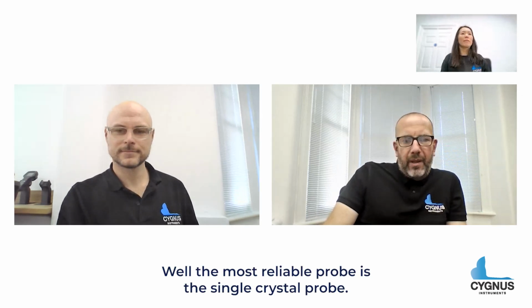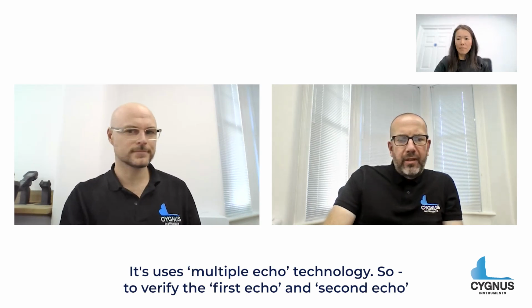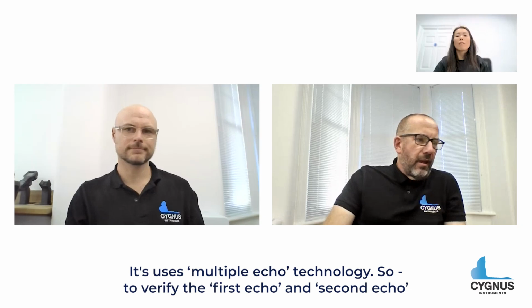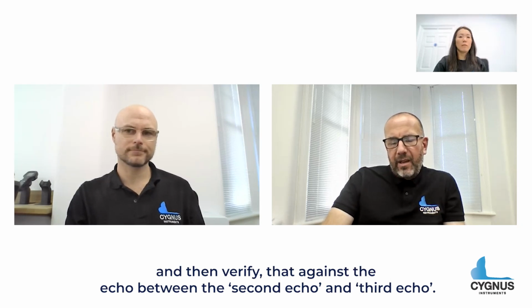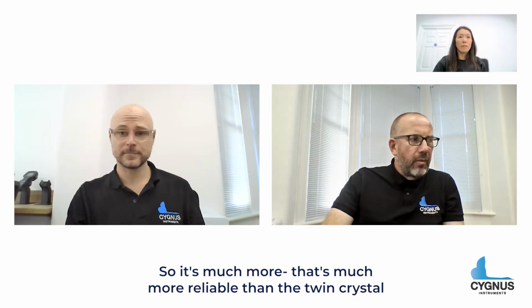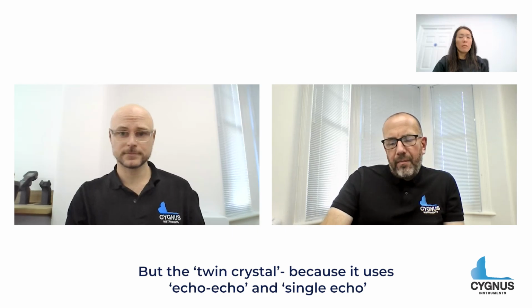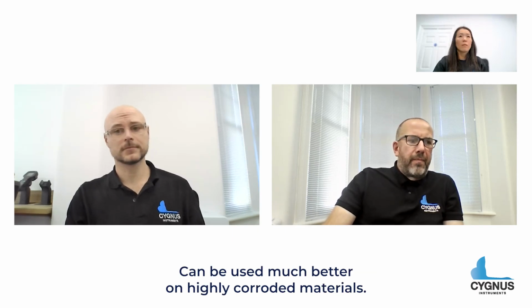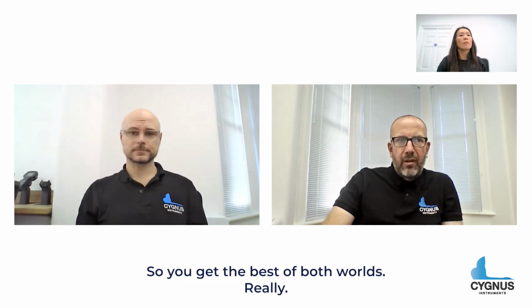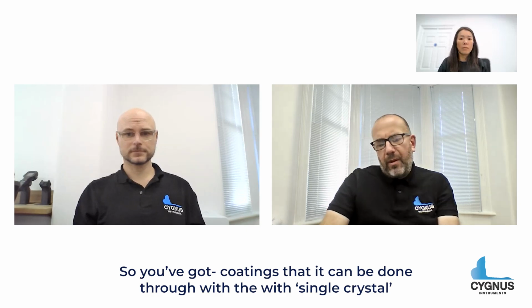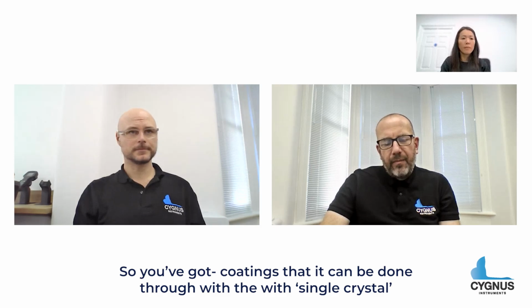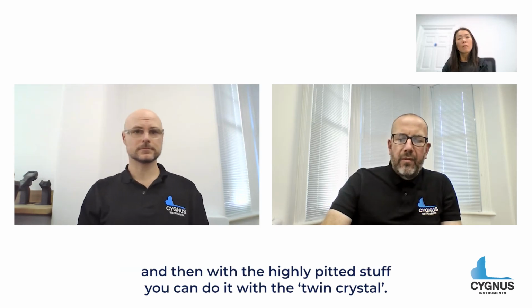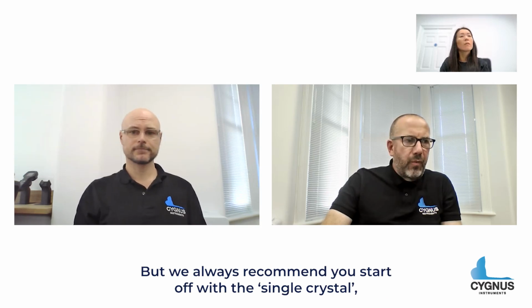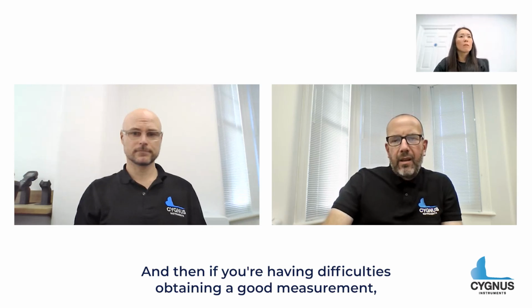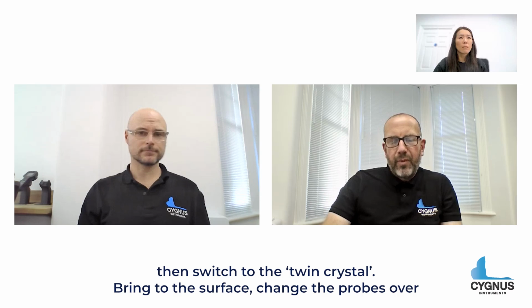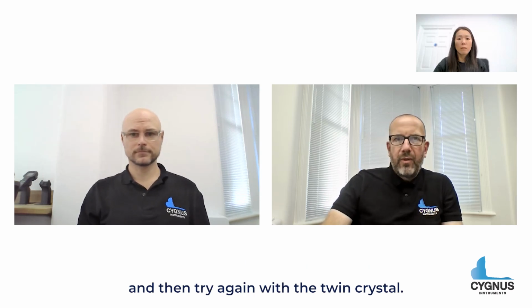Well, the most reliable probe is the single crystal probe. It uses multiple echo technology, so it verifies the first echo and the second echo, and then verifies that against the echo between the second echo and the third echo. That's much more reliable than the twin crystal. But the twin crystal, because it uses single echo, can be used much better on highly corroded materials. So you've got the best of both worlds really. Thick coatings can be done through with the single crystal, and the highly pitted material you can do with the twin crystal. But we always recommend you start off with the single crystal, and then if you're having difficulties obtaining a good measurement, switch to the twin crystal. Bring it to the surface, change the probes over, and then try again with the twin crystal.